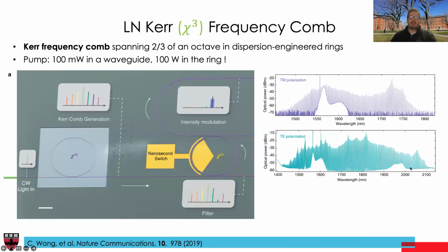And then with these high Q resonators, we have actually demonstrated the first lithium niobate based Kerr frequency combs, as shown here. In particular, in this chip that we fabricated, we have a ring resonator that's coupled to optical waveguides. We come in with CW light, and this ring actually gives us a frequency comb, and this is the spectrum of the frequency comb.